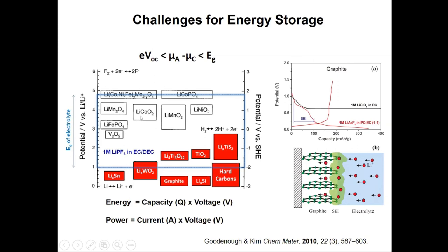But of course, we can stabilize these interfaces if we don't go to quite high potential, and commercialize materials such as these two options, which you can now buy batteries made with that particular cathode material. The other thing to notice is that we currently use a graphitic anode in most all commercial batteries. And this lies below the window of electrochemical stability. It's unique to the properties of graphite, which is that when lithium ions interact with graphite, they never get reduced to lithium metal. They insert as ions in between the van der Waals spaces of this graphitic structure.